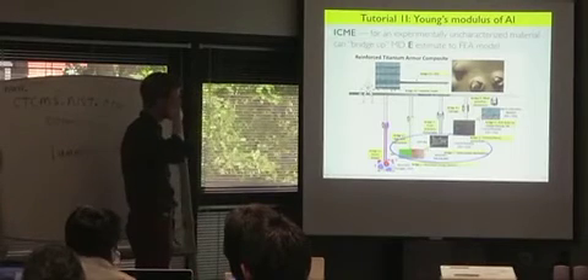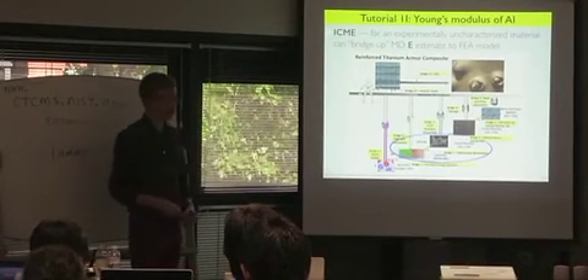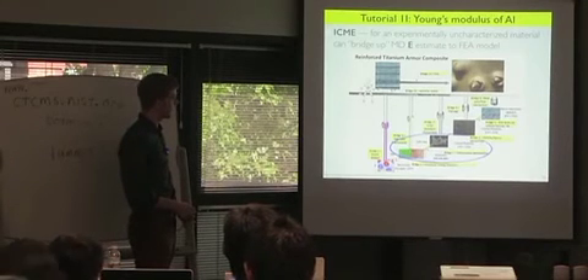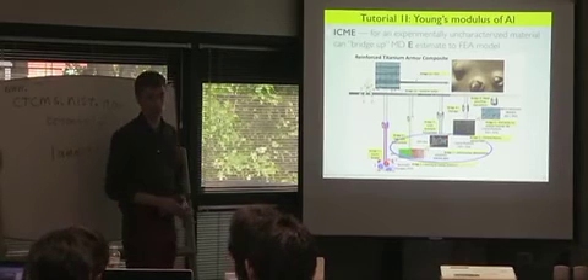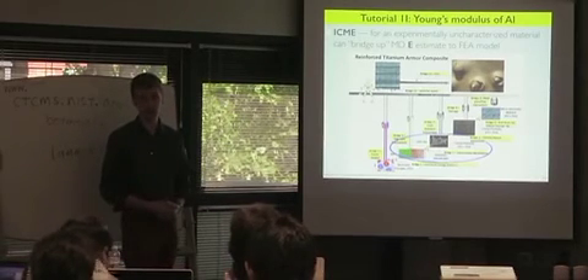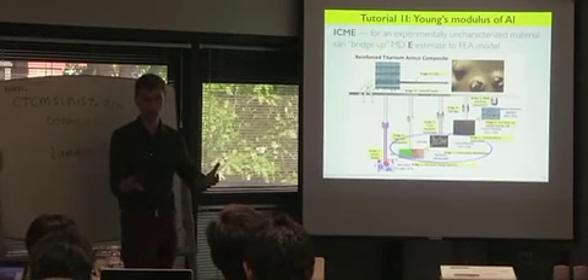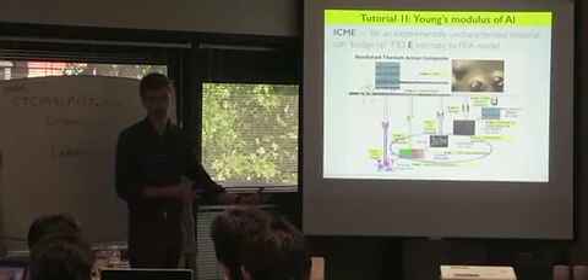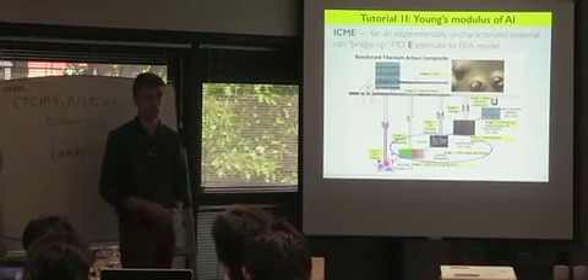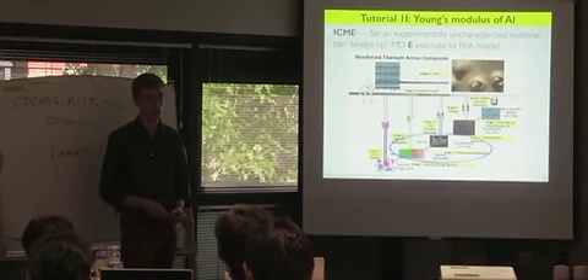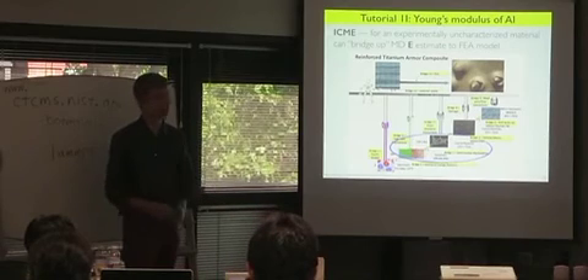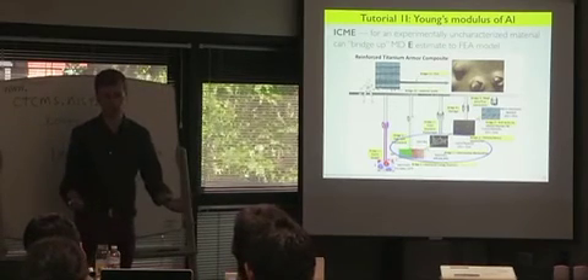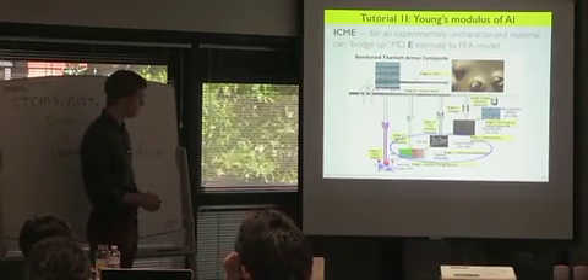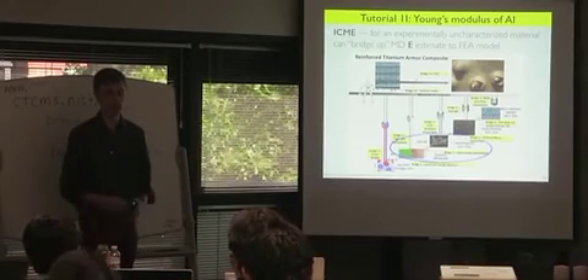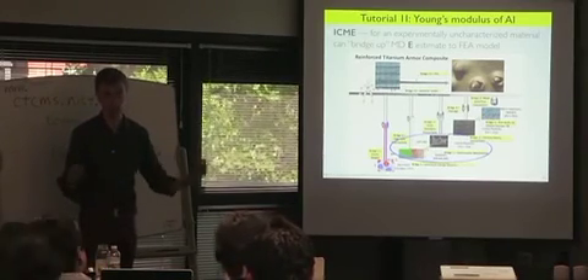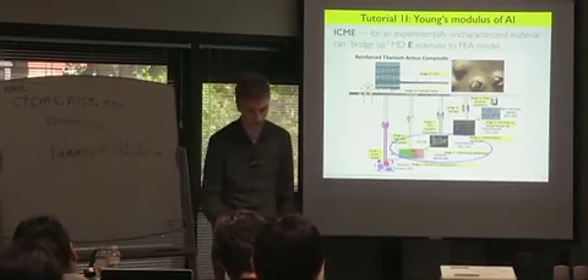Okay, and then just last, very last words, which is how could we incorporate that into an ICME paradigm? Well, we've used molecular dynamics at this length scale to estimate the Young's modulus, which we might then import into a finite element model at a larger scale. So we might design a finite element analysis simulation, and we could dial in the value of the Young's modulus that we computed from our molecular dynamics simulations. Why is this useful? Well, maybe you're studying a new material that hasn't been experimentally characterized, or perhaps a material that's hard to characterize experimentally, or is too dangerous to characterize experimentally, or is under conditions where it's very difficult to analyze. So in a nuclear reactor or at very high temperature or pressure. In which case you could use MD to get the parameters to input into a finite element simulation and then do things over length scales of say centimeters for seconds. So integrating into this ICME paradigm.